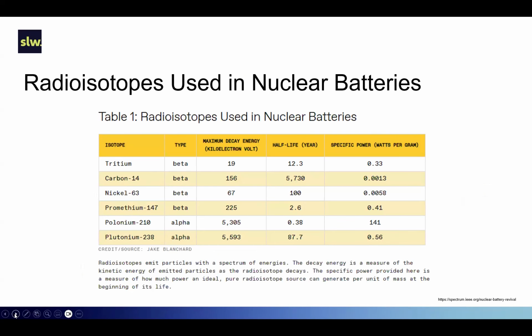So radioisotopes used in nuclear batteries, the most common ones include tritium, which has a maximum decay energy of 19 kiloelectron volts, half-life of 12.3 years, and a specific power of 0.33 watts per gram. Carbon-14 is another beta particle. It has a maximum decay of 156 kiloelectron volts, a half-life of 5,730 years, but a specific power in watts per gram of only 0.0013.